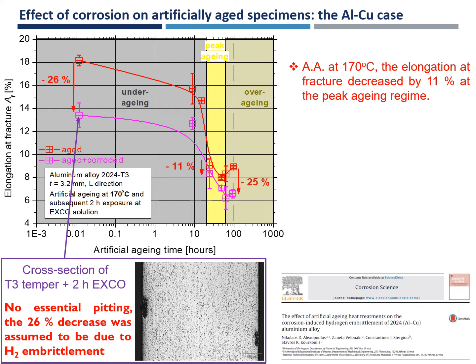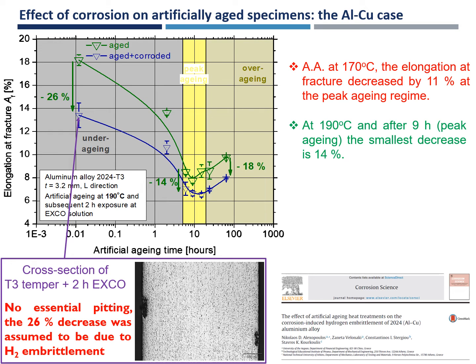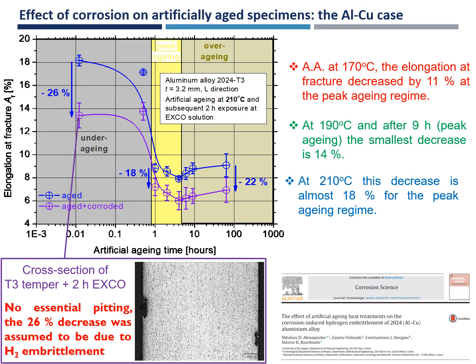Specimens were exposed to 2 hours corrosion exposure time and in 3 different artificial aging temperatures. It was found that the lower corrosion-induced degradation of elongation fracture was evident in the peak aging condition for the 3 different temperatures. However, this degradation increases with increasing the artificial aging temperature, where from almost 11% at 170 degrees Celsius, it was increased to almost 18% at 210 degrees Celsius.